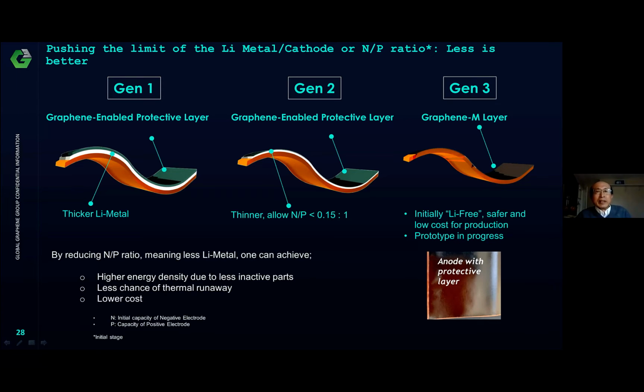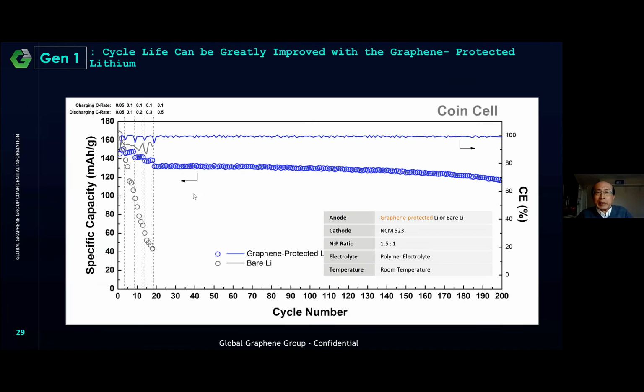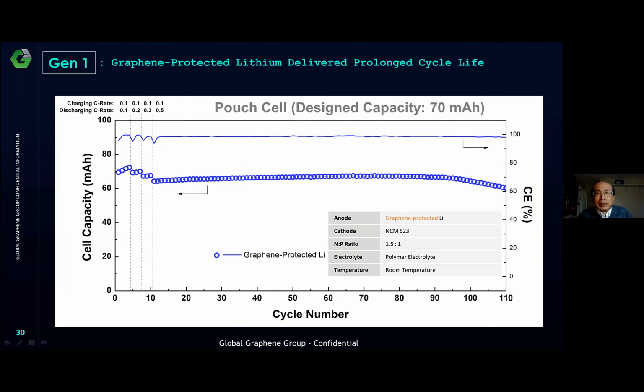And again, these are some of the data that I can show you here. I can share with you full cell data that shows that by implementing the graphene, we are able to achieve very stable cycling behavior. In contrast, without graphene, the battery quickly fails. And then we have other so-called generation 2 and generation 3.